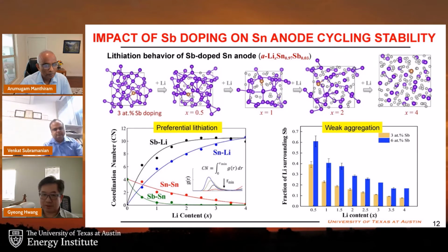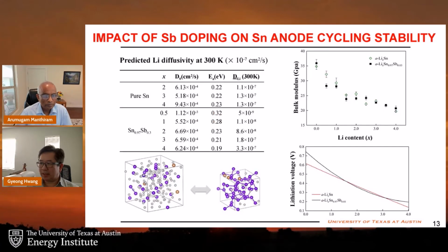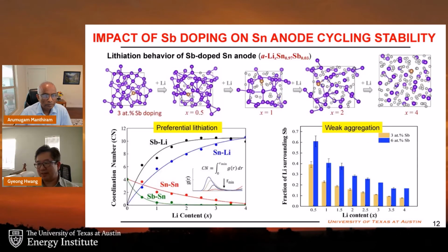I'm not going into the details of the results. The key findings from analysis of these results are that the lithium atoms preferentially interact with the antimony over tin, especially at the early stages of lithiation. And the antimony atoms remain well dispersed in the lithiation and the delithiation process if the antimony concentration is sufficiently low. The weak aggregation and the preferential lithiation tendency of antimony dopant in the tin anode can contribute to enhancing its structural stability during cycling in comparison with pure tin and the tin-antimony alloy cases.